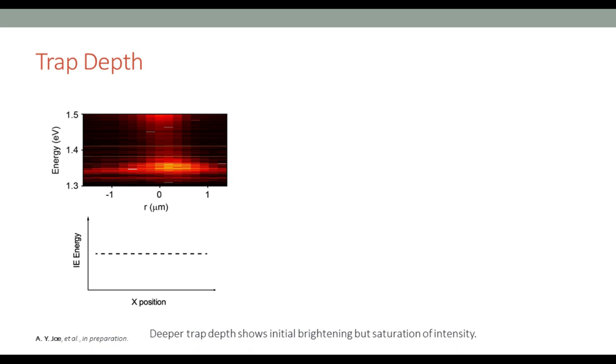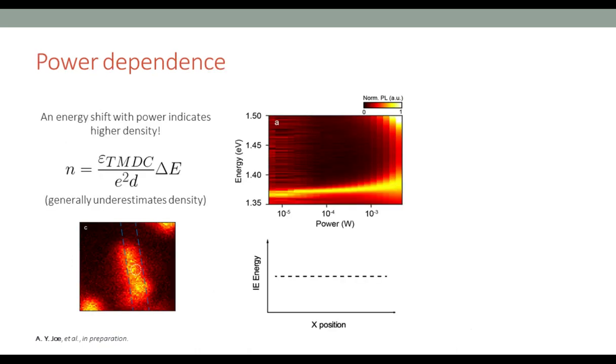So from this, it's hard to extract what the actual density of excitons is. In order to look at the density, we can do a power dependence. By changing the power, we can change the density in our sample, and from this change in density, we should see a blue shift in the energy.